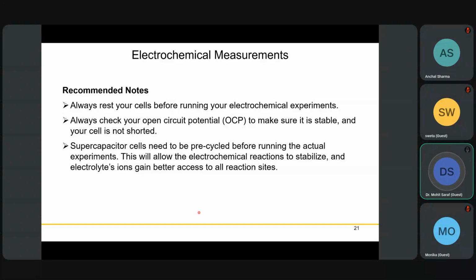For supercapacitors, it is always recommended to do preconditioning or pre-cycling of your cells. Again, the purpose is just to check whether everything is okay with your cell, and those pre-cycling steps also wet your electrode. So your electrochemical reactions will be stabilized, and the electrolyte will be able to access your materials properly, and you can get better results.